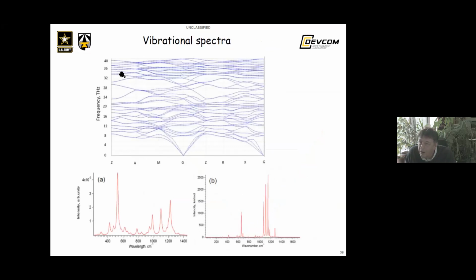So these are phonon dispersion curves. There are no negative imaginary frequencies, which indicates dynamic stability of this structure. And these are Raman and infrared spectra, which are in general agreement with experimental results.